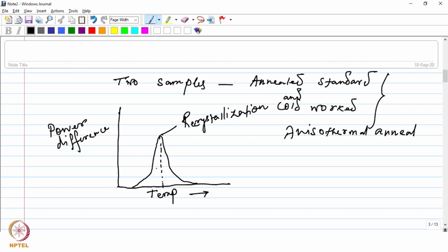But you can see that the release has started even before the recrystallization process, right? Because at every other point below the peak, you have some power difference, right? So that means below the peak also the strain energy is being released. Okay. So that is the recovery stage. As I said before, recovery precedes the recrystallization process, and during recovery also a certain amount of the strain energy is released, and that is what you can see from this curve also, right?